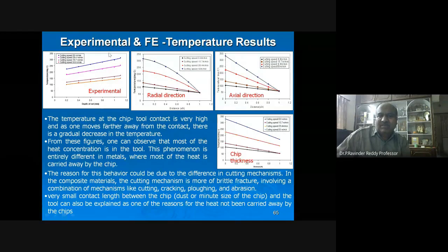So these are experimental values. And we can see from the radial direction how the temperature is varying at different cutting speeds, and similarly in the axial direction. We can also measure the chip thickness, so the chip flowing process. The temperature at the chip-tool contact is very high, and as one moves further away from the contact, there is a gradual decrease in temperature. From these figures, one can observe that most of the heat is concentrated in the tool. This phenomenon is entirely different from metals, where most of the heat is carried away by the chip.